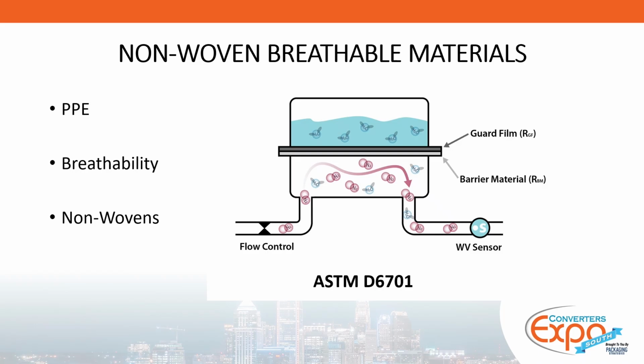in between the water reservoir and the actual material, versus the E96 cup test, that traditional method, where there was a gap, and that was always in question as to what the driving force was. This is more so for non-wovens and breathable materials, and actually some very high transmitting materials used as venting. Sometimes you want to let a lot of moisture out as a vent so it doesn't pressurize a package system.